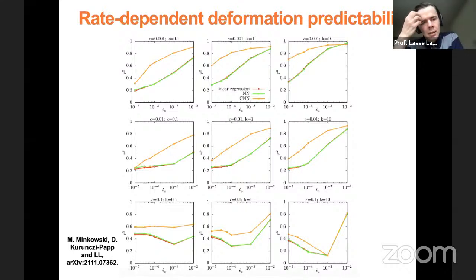So now we can look at basically the same quantity as before. Now we call it R squared, not S, but it's the same thing. So sorry for that. Here, each of these small sub-figures is for a different value of strain and a different value of the stiffness parameter k. And then here we show the R squared as a function of the strain rate. So the general conclusion here is that, first of all, the neural network and the linear regression always give rise to roughly the same result. However, the CNN is able to do better than that.